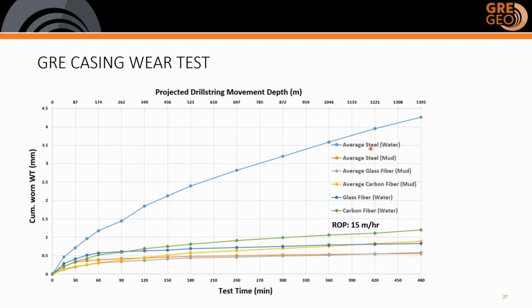The short summary of all the testing can be seen in this graph. And as you may see, in the water, the steel wear is one of the biggest among all the tested materials. And if you look at the glass fiber in the water and in the mud with the presence of sand, we may see that the wear and damage to the pipe is minimal. The reason for that is that the glass fibers are quite smooth and quite solid in order to withstand the wear effect of the string.